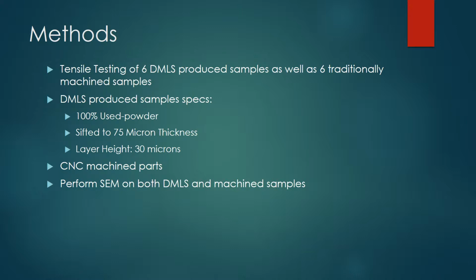For our method, we used 6 DMLS produced samples, as well as 6 traditionally machined samples. The DMLS produced samples were sponsored by 3D Systems, and we used 100% used powder, which was sifted to 75 microns, with a layer height of 30 microns. For the traditionally machined samples, we used the CNC to machine the other dog bones. And then finally, after performing tensile testing, we performed SEM on both the samples in order to compare images.